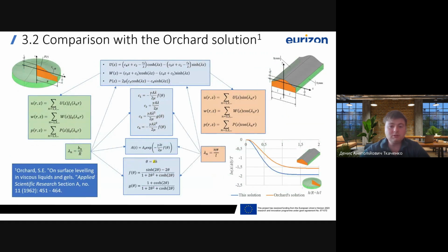This process leads to an explicit differential equation for the amplitude of a surface irregularity. Its solution, shown in the final formula, demonstrates exponential decay of the amplitude over time. The decay rate depends on material properties, geometric parameters, and the function phi of theta, which captures the effect of layer thickness relative to the feature size.